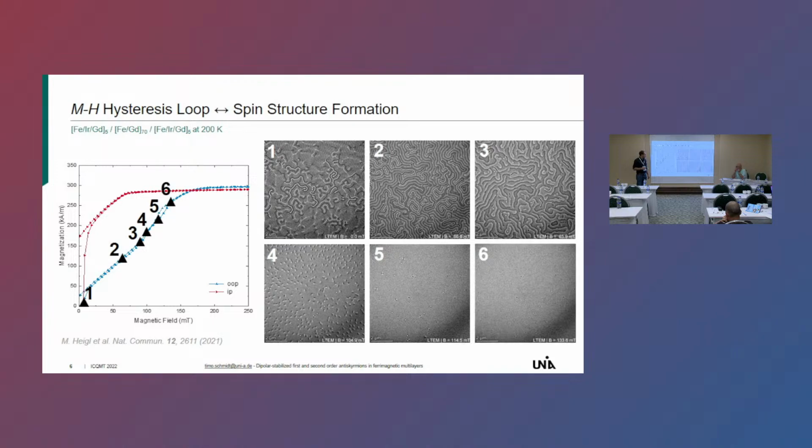At the next step, if you increase it one step further, the anti-Skyrmions also annihilate because they are not as stable as Skyrmions. So we can translate that into some stability ranges. Our bubbles have the lowest stability, in this range, around 100 milliteslas of magnetic field.